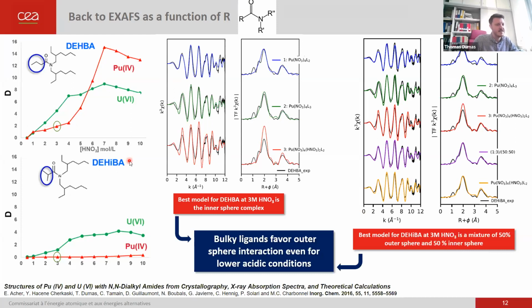And the outcome of this is that we have a better understanding of what the alkyl chain does on the plutonium speciation in the organic phase. In fact, bulky ligands around the branched alkyl chain will favor outer sphere interaction against the inner sphere interaction that you will form if you have only a linear alkyl chain.